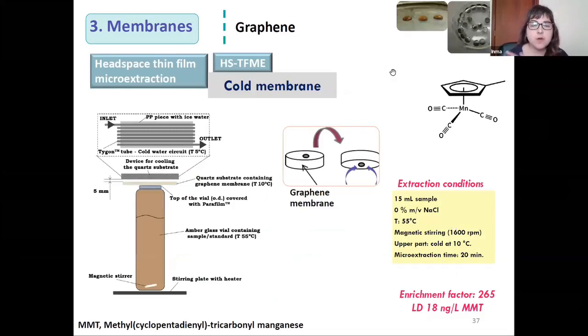Another research work derived from the previous one was based on head-space thin film microextraction. In this case, we analyzed this organometallic compound, methylcyclopentadienyl manganese tricarbonyl, MMT, which is an octane enhancer used in fuel. So it is sometimes interesting to determine its concentration in some environmental waters. So here we have the sample solution, and in this upper part we have the quartz sample carrier with a graphene membrane immobilized in the interior part, exposed to the headspace of the solution.